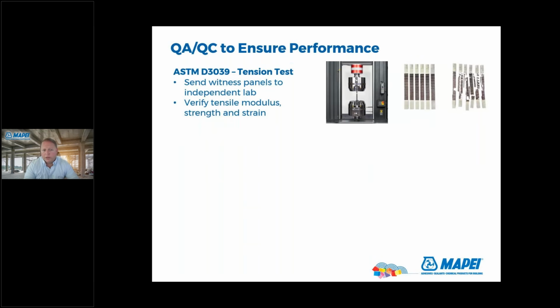So, quality assurance and quality control items. There's ASTM D3039. This is a tension test. This is where, as a contractor is installing FRP, he'll make witness panels, which is just a 12-inch by 12-inch piece of fabric. We'll put it between 2 pieces of plastic mylar, and that will get sent to the lab. And the lab will take that sample and cut it into little pieces, and then they'll pull it apart. And they're going to measure the modulus, the strength, and the strain.